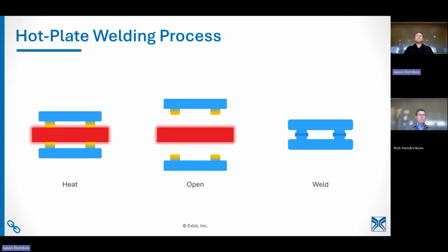And oftentimes what we have people do is design the weld rib width to be a little bit wider than the wall thickness of the rest of the part. That way, if your weld strength is more in the 95 to 90% range, the extra thickness in the rib will get you to the 100% strength. So if the wall thickness is strong enough to survive the impact, then the weld joint should too. Most of the time when we do strength testing on plastic welded parts, the joint doesn't fail. Somewhere else on the part breaks apart. Yeah, parent material, right?